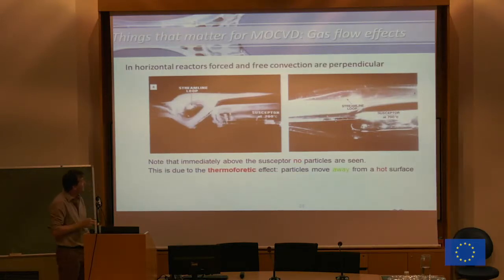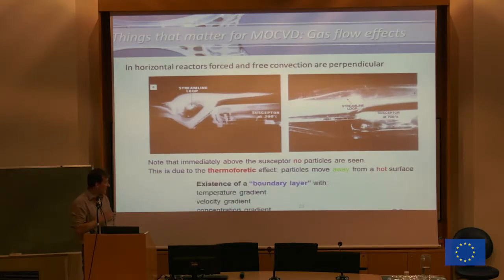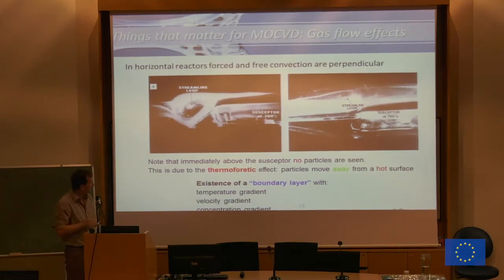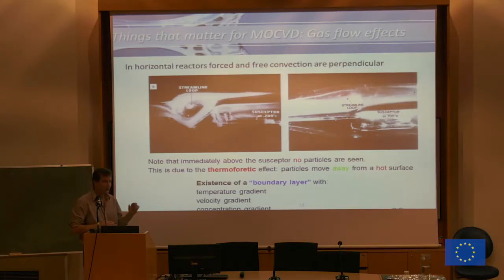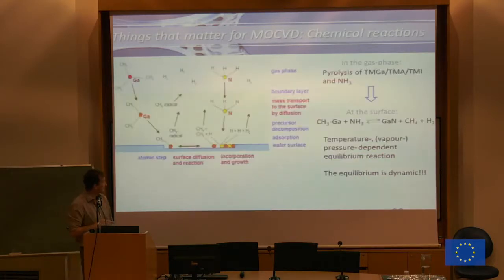And what you can clearly see, what I wanted to point out, is that here above the susceptor, there is a boundary layer. There is a layer where you do not have these white particles. And it's a very important concept in MOCVD because in this boundary layer, you have a temperature gradient and a concentration gradient, which are both crucial to controlling your process. So that is mainly what I wanted to say of the fluid dynamics, is that we need to take into account that this one exists.